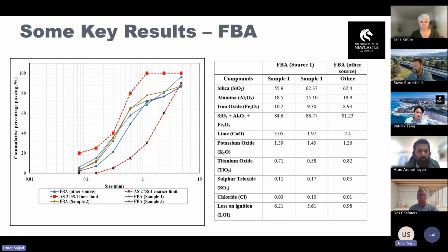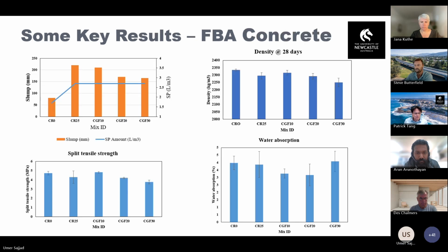This is the particle size distribution results of the furnace bottom ash obtained from a couple of sources, and from one source we have done a couple of analyses. We have a chemical composition and also the particle size distribution. So we can see that furnace bottom ash lies perfectly within the Australian standard limits of coarser and finer aggregates. So as per standards, we can easily use it as fine aggregates.